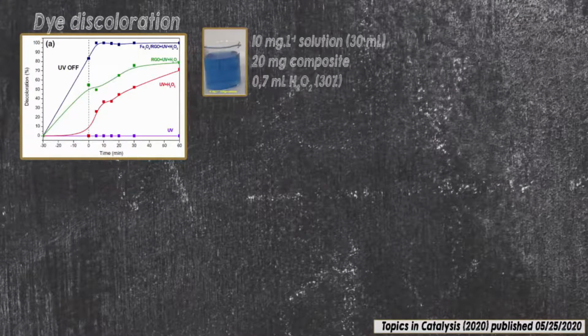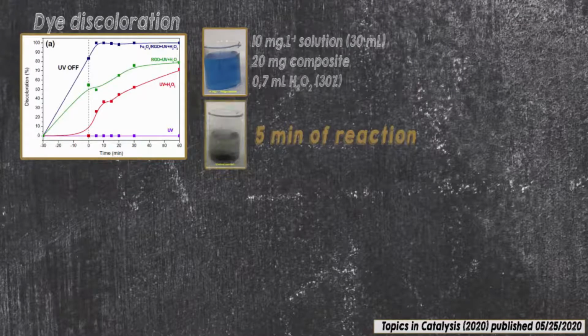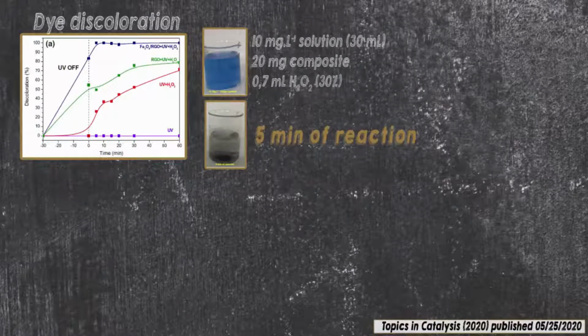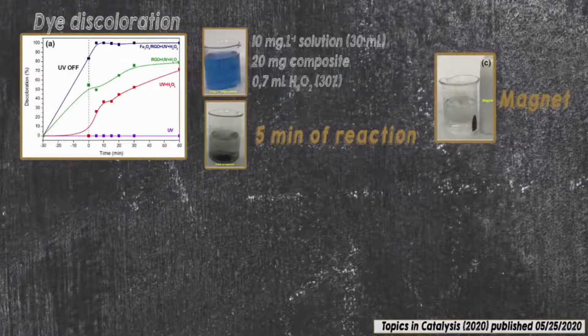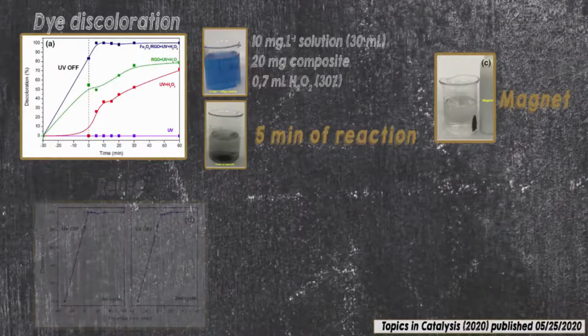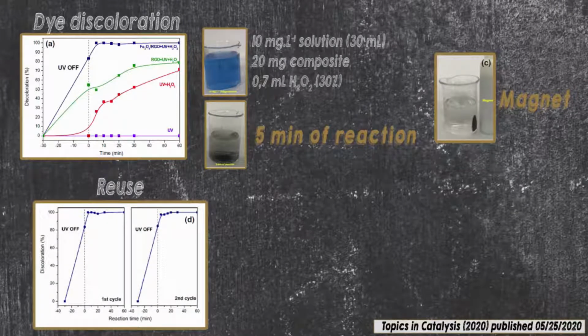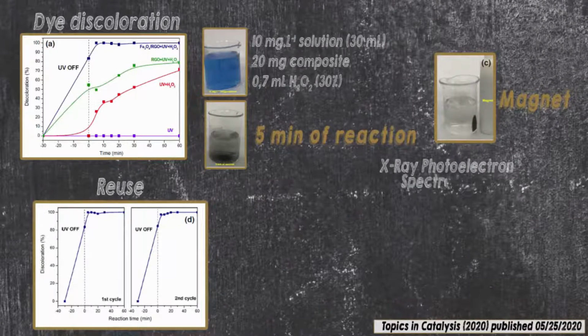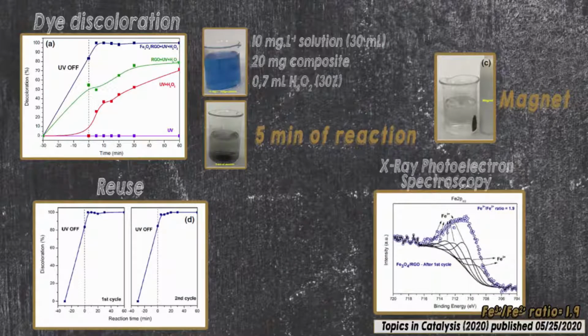This graph here shows the indigo carmine dye discoloration as a function of time. We can note that with 5 minutes of reaction, our composite discolorated 100% of the indigo carmine dye solution. After the first reaction, we recovered the catalyst with a magnet and reused it in the second cycle. Once again, 5 minutes of reaction were enough to discolorate the indigo carmine dye solution. X-ray photoelectron spectroscopy, which is a surface analysis technique, shows that we have an iron 3 plus to iron 2 plus ratio of 1.9, which means that magnetite particles were preserved even after the first cycle.